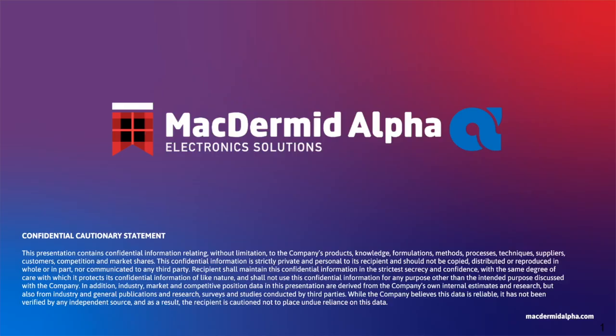Yeah, good question. So I think essentially it boils down to stress management and stress mitigation. BGA surfaces, as you know, typically the packages are bigger, the die sizes are bigger. There is difference in CTEs, organic surface versus a lead frame surface. So basically, the way we have addressed this challenge is to fine tune the modulus. For example, that's the easiest way to explain this. Modulus is a very good indicator of how your material is managing the stress that's developed in the package. So essentially, it's a measure of the stiffness of the material once it's cured. And for example, the BGA packages may have a tendency to warp because of the size and also the exposures that it's exposed to in terms of thermal temperature exposure.